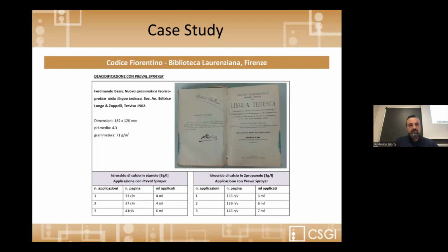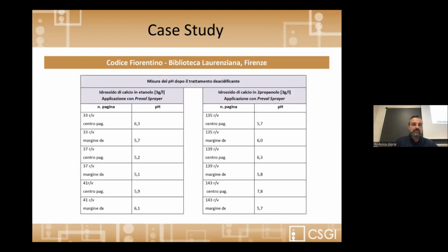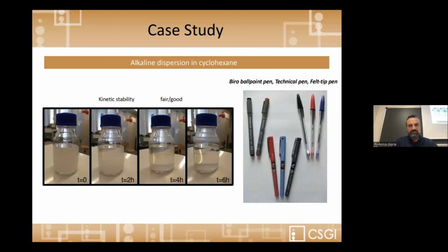In order to define the right setup for working on that, we started working on paper with similar composition, the same grammage, the same pH condition, in order to define the best procedure and the right amount to apply in order to have a good, mild variation of pH to reach neutrality. This was the approach we followed, that was at the end successful, and the Florentine Codex was deacidified.